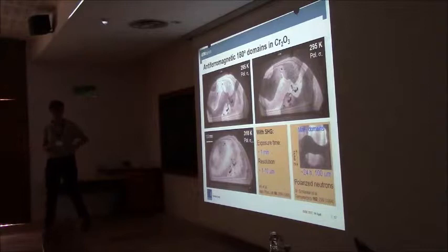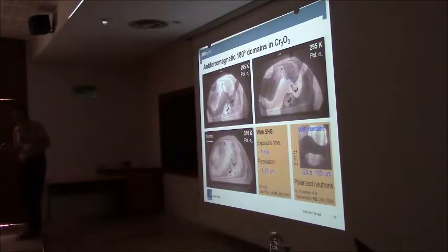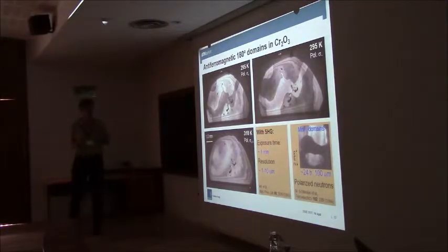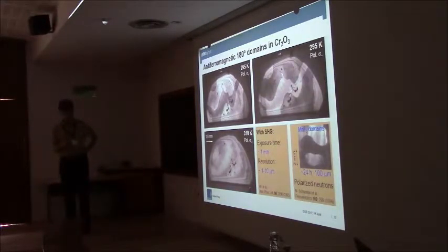And then, because it's an optical technique, you can just image the second harmonic light with a camera. The only difference is you just put a filter in that blocks omega and just passes 2 omega. Then you get images of antiferromagnetic domains of this type. And this is really otherwise impossible.